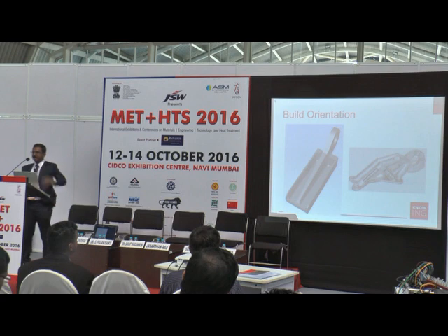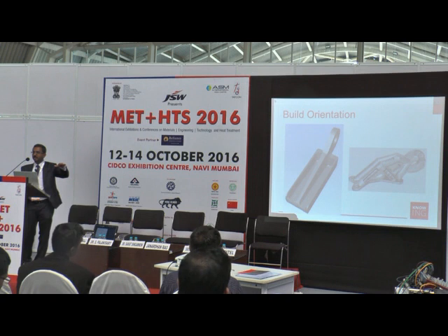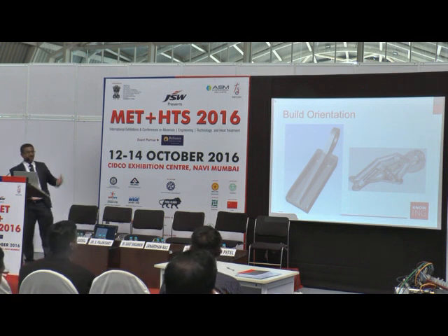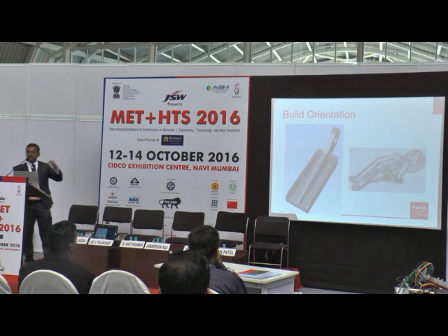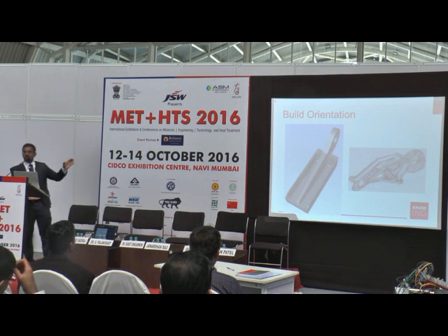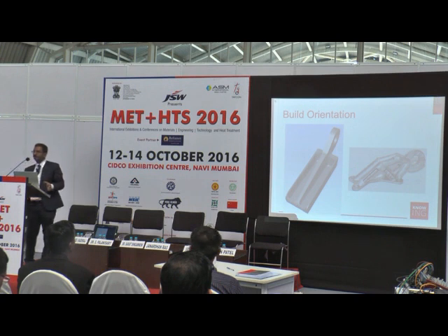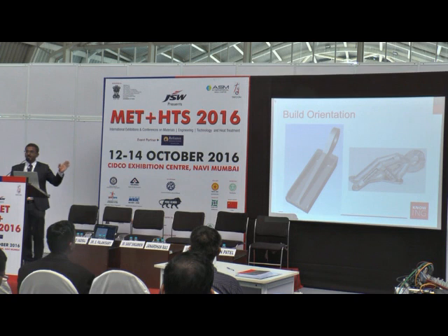So, build orientation. Again, somebody asked earlier about the build orientation. As you know, all the parts are not just flat, horizontal. They have vertical columns, inclined columns, so you have different shapes. As you can see in this particular component, just a lever bracket. The same bracket, with topology optimization, as Nayan Patel mentioned earlier, can be optimized into different dimensions or a different shape, which can only be produced through the additive manufacturing process. You can also see hollow structures inside that component, like a truss, which is only possible through additive manufacturing. It cannot be done by any other process. So that's a significant advantage there.